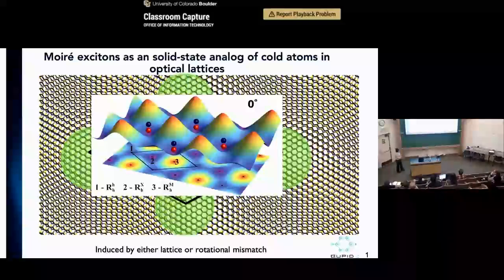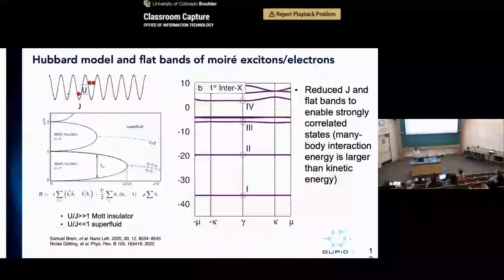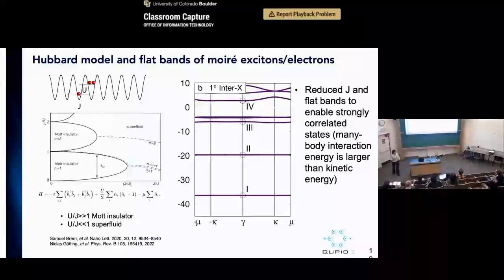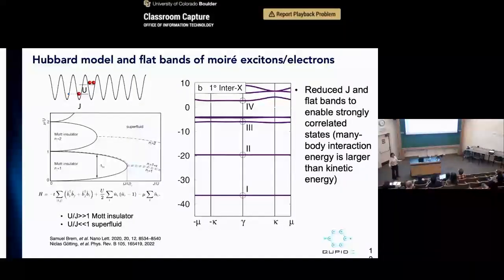The reason you want to trap them in the Moiré superlattice is that you want to make the excitons move slower, because as they move slower, they interact more strongly with each other. It's as if you are running really fast, you're not going to pay attention to people on the sidewalk. But if you're forced to move around very slowly, you would have to interact more with the people around you. It's the same for this exciton. We force them to interact more strongly by reducing the bandwidth, or making the band flat. Because of the Moiré lattice, you reduce the J, which makes the exciton more localized.